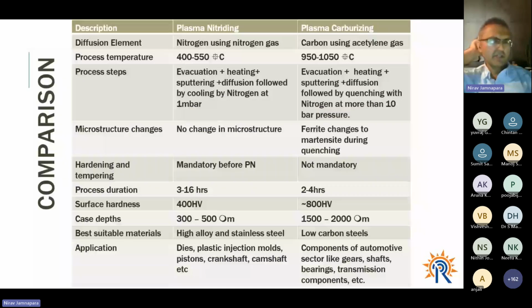Because this is a surface hardening technique, we also wanted to compare plasma nitriding and plasma carburizing. Both are interstitial diffusion processes, but nitriding is possible at lower temperatures, whereas plasma carburizing is possible at very high temperatures from 950 to 1050 degrees Celsius. Several steps are involved, mostly similar, but in plasma carburizing it is high pressure gas quenching with more than 10 bar pressure. The microstructural change is that ferrite changes to martensite. In plasma nitriding, there is no change in the microstructure except the nitriding case.